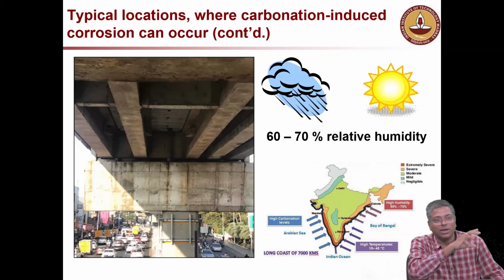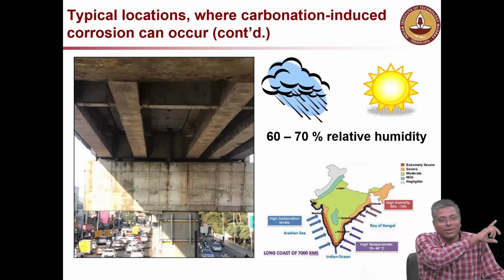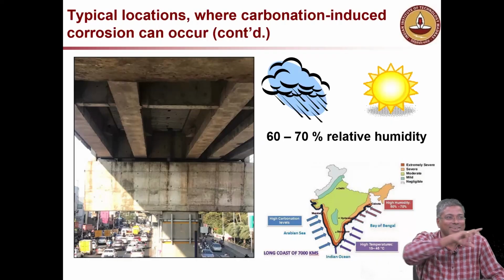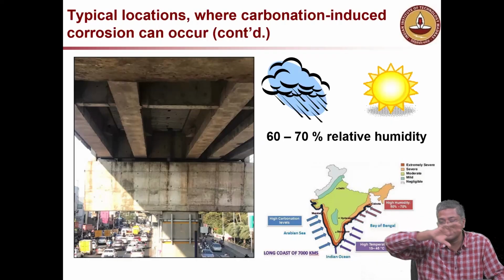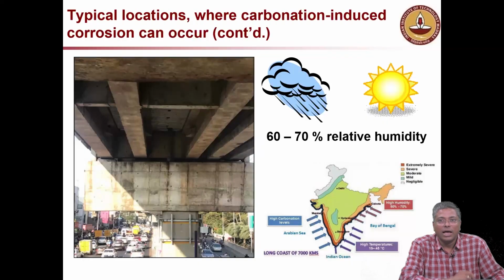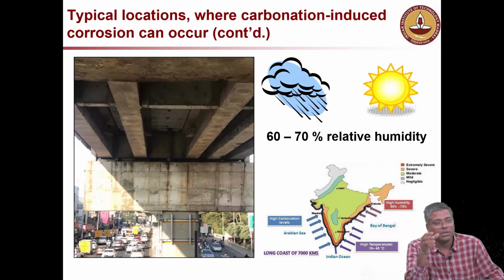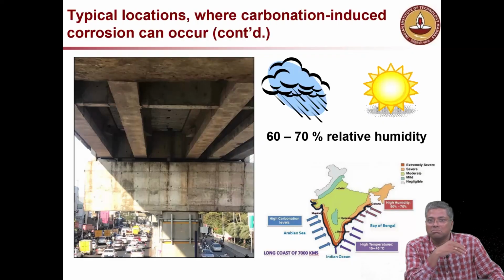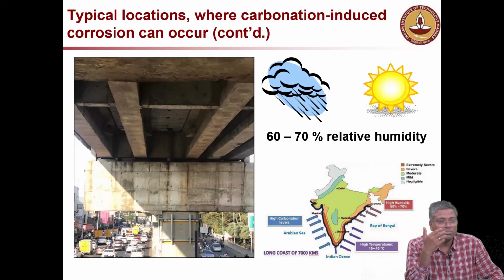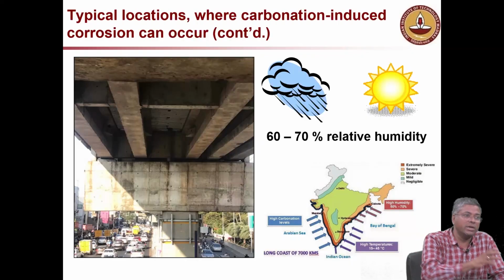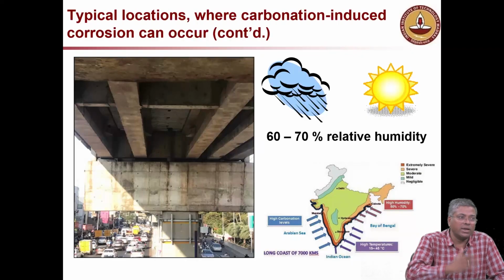We have done something from the seashore in a car, we drove and measured the CO2 level along the roads, and it's very, very high. And if the relative humidity inside the concrete is around 60 to 70%, that is the worst scenario. In most cases, like in Chennai, it is like that. If you go to Delhi, maybe not. It will take a long time to carbonate because it's a very dry environment. If you go to Hyderabad, maybe not. So you have to look at the ambient humidity condition to see whether you should worry about carbonation or not.